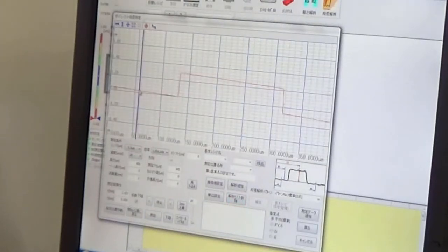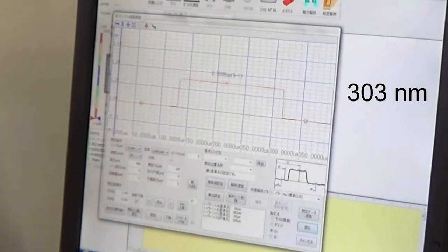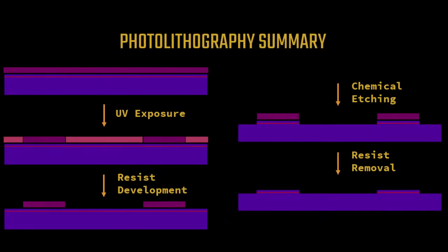This measurement is achieved by a scanning tip. In this example, the height difference between the etched and unetched surface is 303 nm.